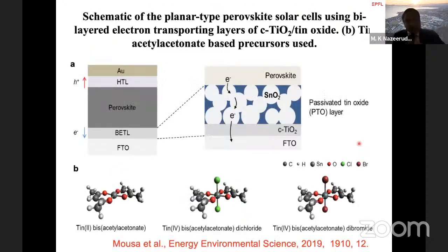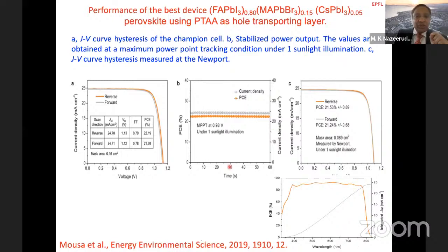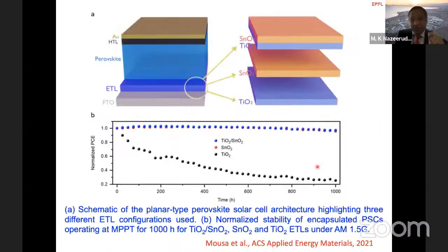Similarly, I go very quickly on the ETL layers. So the ETL layer, we were using the compact TiO2 followed by SnO2 and then passivated tin oxide. And here we have shown efficiencies in the range of 22%, which was certified at Newport again. This was in 2019. Now we have a new configuration, which is shown here. And this appeared very recently, it's online.